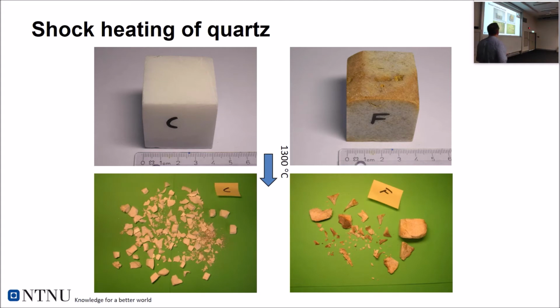So one of the things we did was making cubes of quartz, cutting them to have the same mass, same size. Shock heating this in induction furnaces, 10 minutes at 1300 degrees. This is how the quartz goes up. There's no mechanical treatment of this, it's just a natural reaction to heat, and you see there's a difference between this hydrothermal quartz, which fractures a lot, and this quartzite that doesn't fracture.